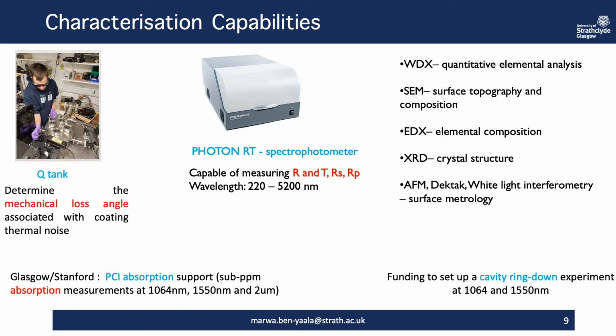So for the characterization of the deposited thin films, we are currently using a Photon RT spectrophotometer that is capable of measuring the reflectance and transmittance, both with and without polarization. And this spectrophotometer covers a wide range of wavelengths from 220 to 5200 nanometer, and also has the flexibility to measure with variable angular configuration.